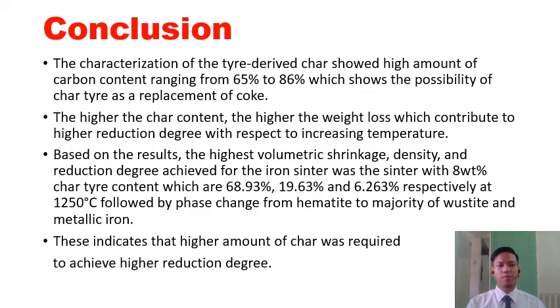As for the conclusion of this project, the characterization of the tire-derived char actually showed high possibility of the char tire as a replacement of coke due to its high amount of carbon content, ranging from 65% to 86% from the carbon analyzer test. Second, this experiment proved that the higher the char content, the higher the weight loss, which contributes to higher reduction degree with respect to increasing temperature.